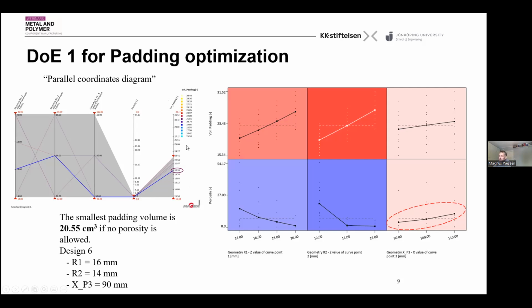But the question is, of course, if this is the best optimum or the robust best optimum which I can have. But then if you evaluate these main effect diagrams again, you can see that, yeah, these are quite obvious. When you increase the radii, the porosity goes down and the padding goes up. That's clear. But you can also see that whenever I go in this direction, the porosity goes up. But it also means that maybe I could have an even better solution if I go even lower. So I haven't found the best optimum.